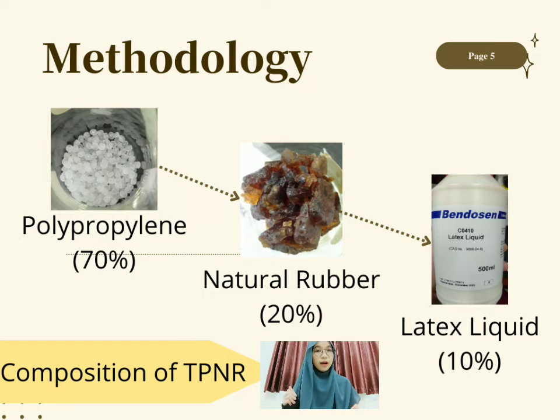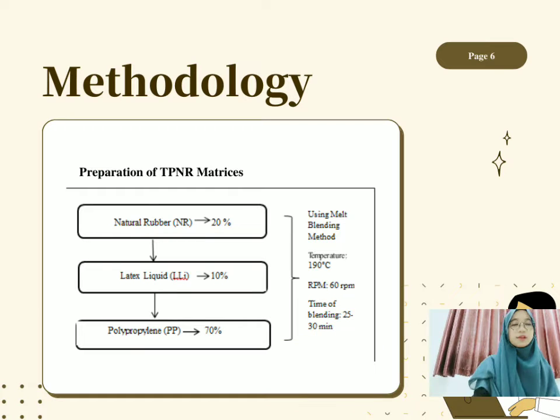To make TPNR, we need 70% polypropylene, 20% natural rubber, and 10% liquid latex. Now we will move to how to prepare the TPNR matrices. First, we cut the natural rubber into small pieces, and then the cut natural rubber is put into the mixer with polypropylene and liquid latex. Then, using the melt blending method, we blend it for about 25 to 30 minutes at a temperature of 190 degrees Celsius and 60 RPM, and after that we get the final TPNR.